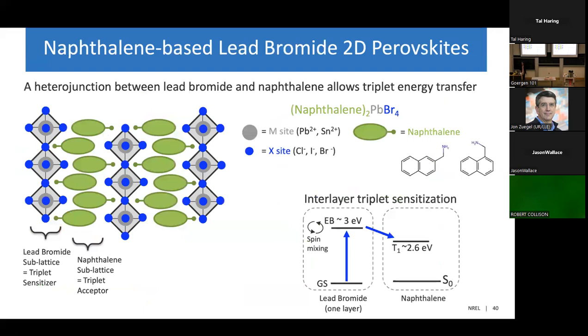So I want to talk specifically about a naphthalene-based lead bromide 2D perovskite composition. The energy diagram is shown down here on the bottom right. So the exciton band for a single layer of lead bromide is around 3 eV, and then the triplet state for naphthalene is around 2.6 eV. So that gives us a pretty substantial driving force for triplet energy transfer across this interface.